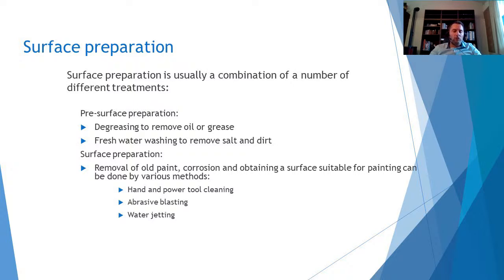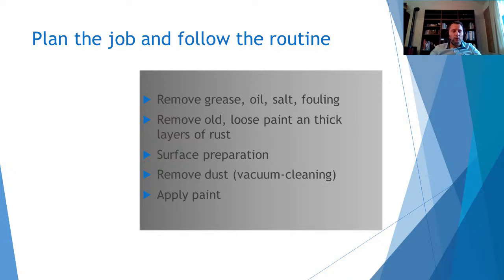Surface preparation is usually a combination of a number of different treatments. We have a pre-surface preparation or pre-cleaning. Its purpose is to remove any extraneous loose material from the surface of the substrate and any potential contaminant. And the surface preparation, that is the target, is to increase the surface area by increasing the roughness and anchor pattern of the surface. Planning the job and following the routine is very important. Here you can see the process for a good steel preparation and surface preparation. Remove contaminant, remove all the loose paint and thick layer of rust, surface preparation, remove the dust through vacuum cleaning, apply paint.